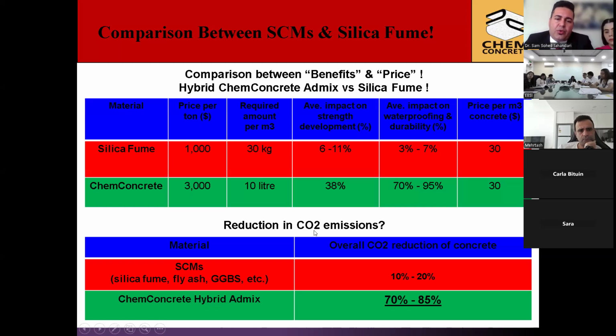One of the most followed ways to reduce the carbon dioxide emissions in the concrete and construction industry is to use supplementary cementitious materials like silica fume, fly ash, slag, or others. But research has proved that these supplementary cementitious materials like fly ash and slag can reduce CO2 emissions by 10 to 20%. But in case of using ChemConcrete Hybrid Admixture, we have done comprehensive analysis, and it's been proven that it can reduce the overall CO2 by 70 to 85%.